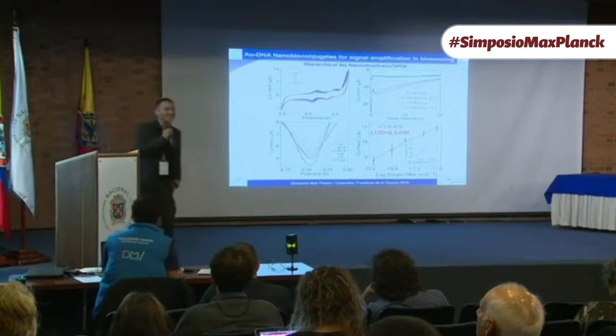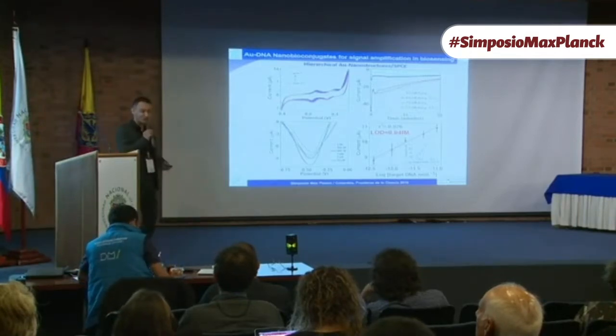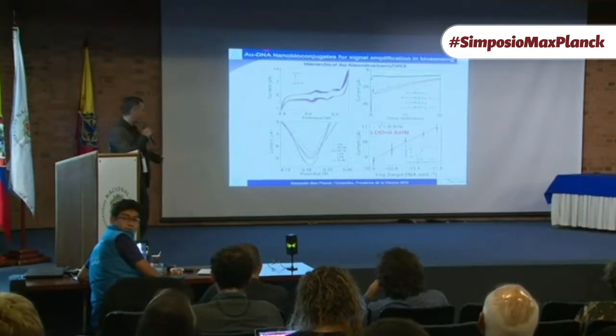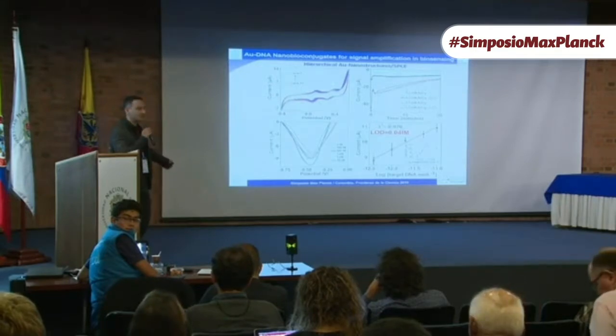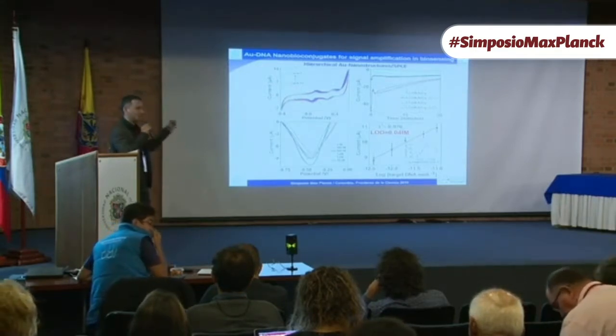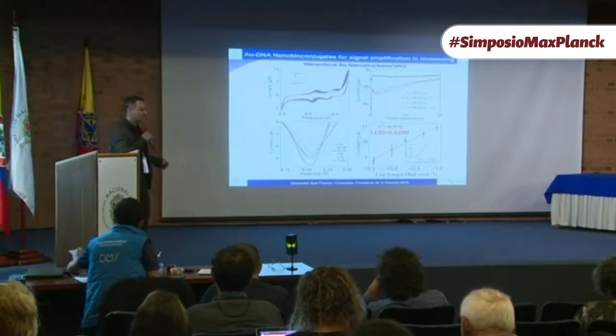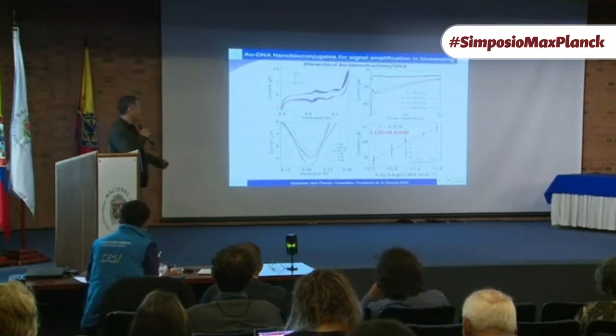A screen printing carbon electrode decorated with hierarchical gold nanostructures, and we assemble the genosensor on top. For this purpose, we electrodeposit a semiconducting polymer on top and electroplate these hierarchical structures. That is not here because it's not animated, the PPT. So at the end, by differential pulse voltammetry, we can get a calibration curve with 0.04 femtomolar concentration. It means we are at the point that is relevant from the clinical point of view, and we are ready to test real samples.